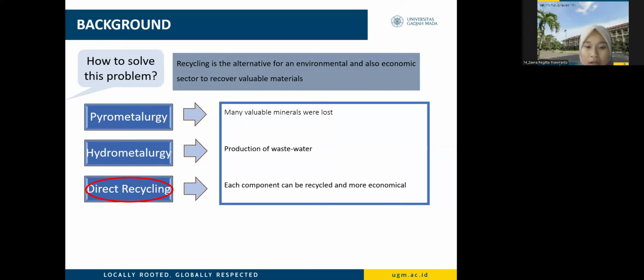The pyrometallurgy method utilizes heat treatment up to 1500 degrees for the recovery of valuable metals, which makes all components such as the anode, organic binding material, separator, polymer binder, and electrolyte burn off and be lost. It consumes high energy and is an expensive process. The hydrometallurgy method uses various acids to break the crystal structure and produces higher recovery than the pyrometallurgy method. However, there is a considerable production of wastewater associated with it. So this method is also not very effective.